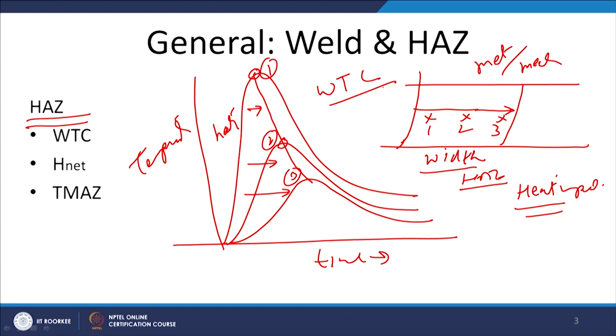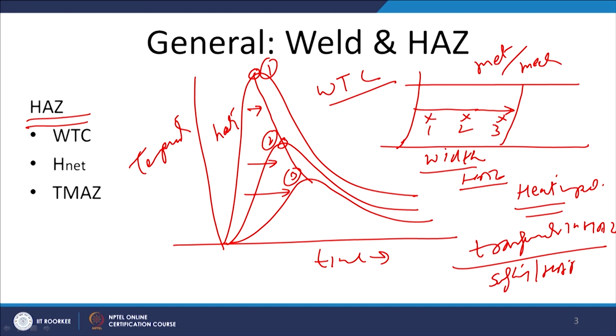Weld thermal cycle to a great extent affects the HAZ characteristics, whether it will be causing which kind of transformation in the HAZ, and whether it will be causing the softening or the hardening of the heat affected zone, development of the residual stresses or cracking tendency accordingly. Embrittlement also is caused by these HAZ transformations. There are ways to regulate the weld thermal cycles associated with the heat affected zone during the welding process, and for that purpose we use preheat.